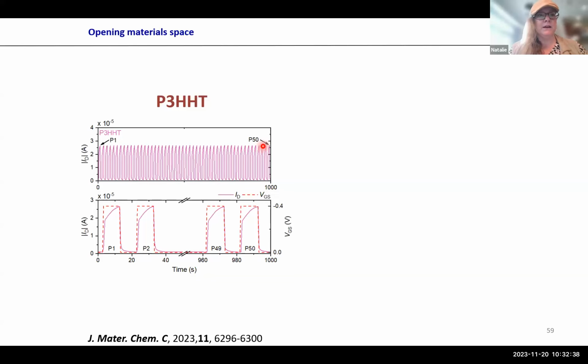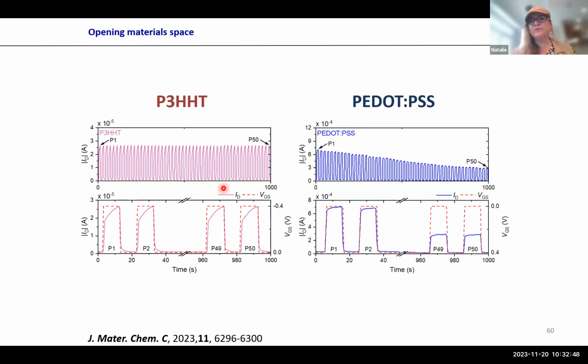So over 50 cycles, you see you can get ions in, ions out, ions in, ions out, and therefore you oxidize the polymer. This is very different to PEDOT:PSS, which is a material that I anyway hate, where you see that you really start to lose current over the cycling. And that's really shown here, how drastically the current changes when you do the cycling. And one reason is that you lose some of the PSS and other things. So it's a lot of issue here. It's the mechanical robustness, and it has to do with the volume change.